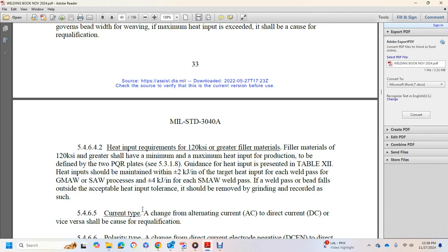Heat input with the requirement of 120 KSI or greater filler metals: the 120 or greater shall have the minimum and maximum heat input with production to be defined with the two procedure qualification record plates. Guidance for the heat input is present in Table 12. The heat input should be maintained within plus or minus 2 kJ per inch of the heat target input.